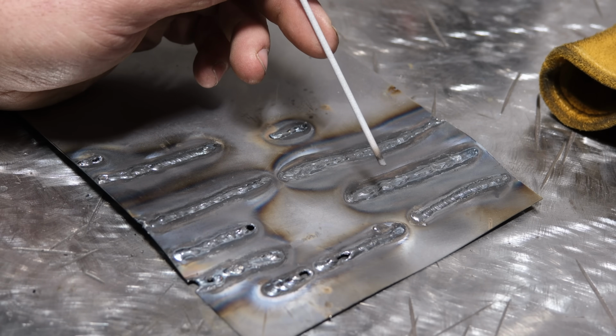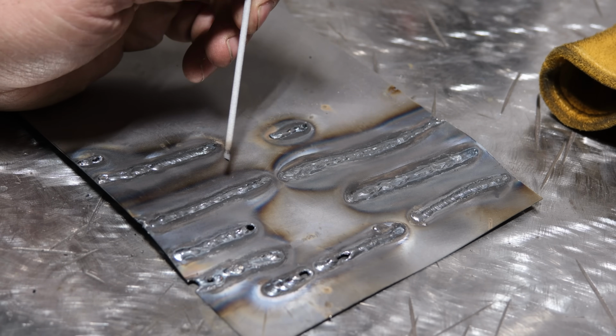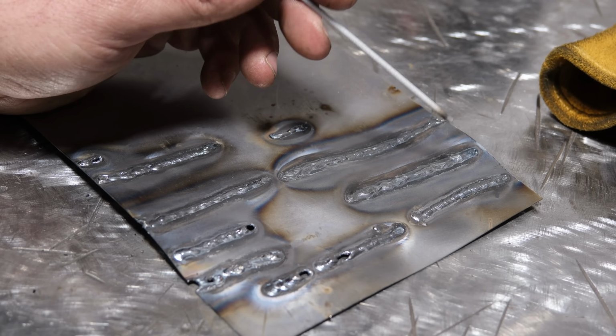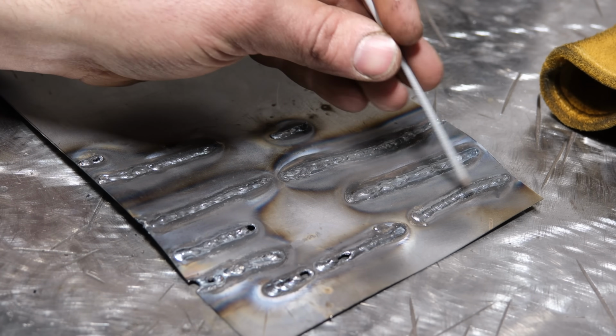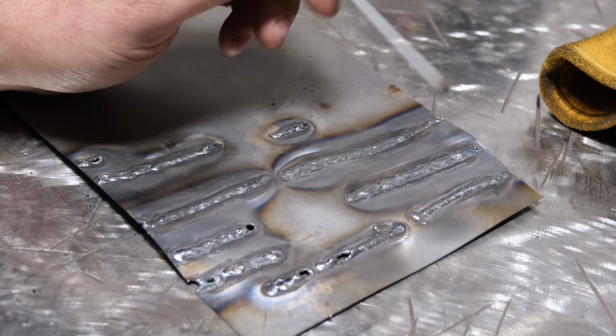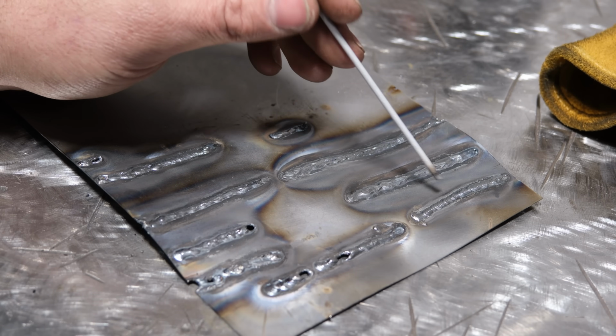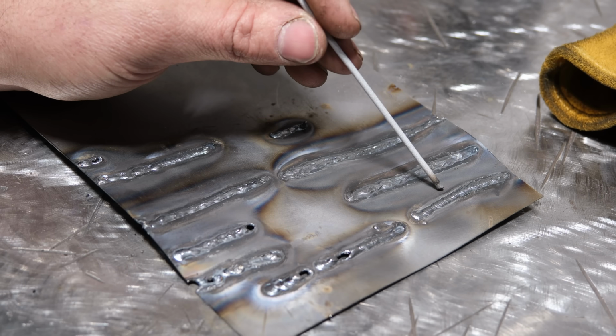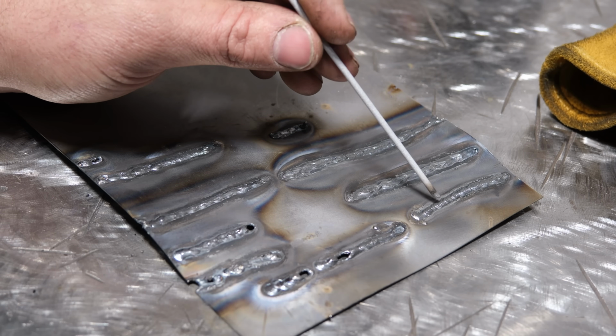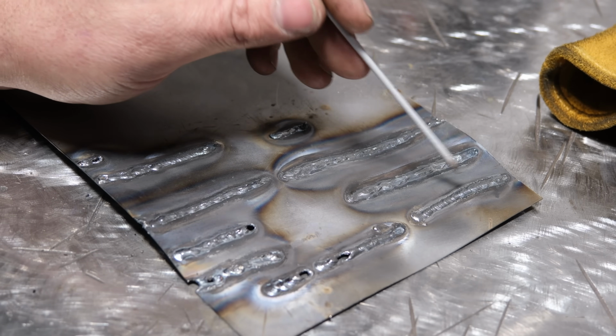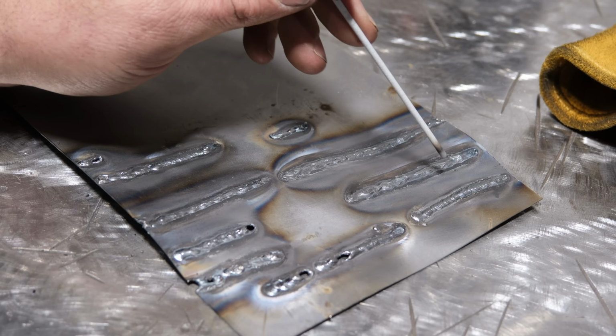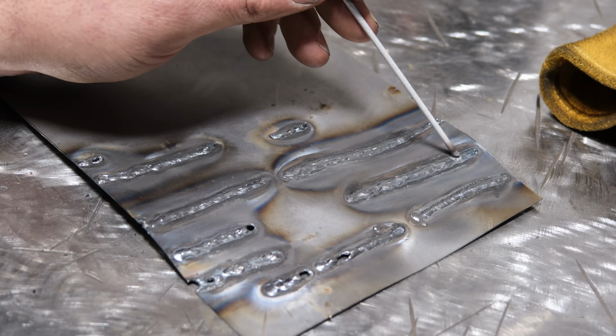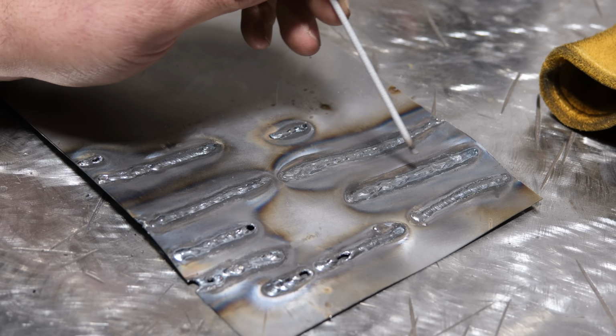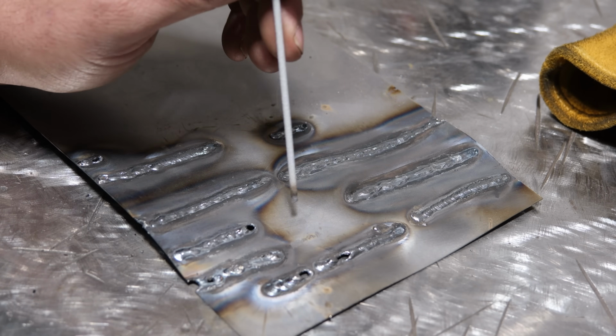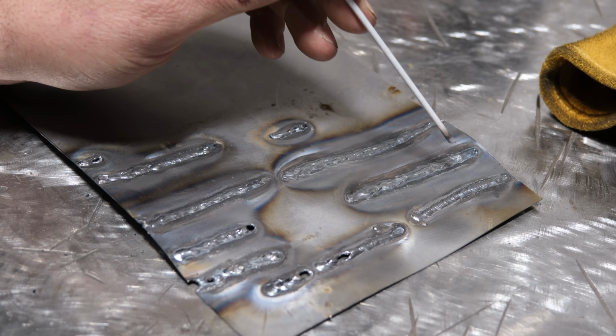Now, I fooled around between 25 and 30 amps, and on this base plate, I found that the sweet spot for 6011, and I believe this is 6011 right here, was somewhere around 26 amps. The problem is at that low of amperage, it was very easy for the arc to wander in front of the direction you're traveling and not push back at that slag. It stabilized better at 30 amps. The problem is that it was just a lot hotter, a lot wider of a weld. And for just this thin a material to run a bead, it just wasn't going to work.